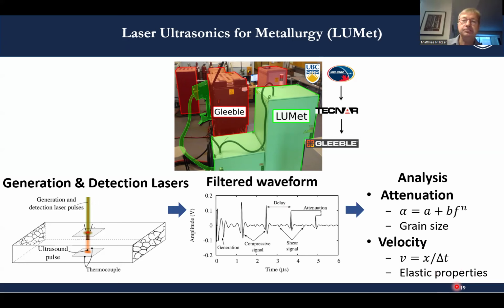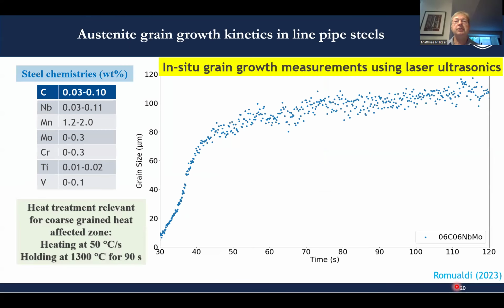when there is a texture change during recrystallization or phase transformation, we can record this as well. And we did high throughput studies for line pipe steels, where we looked in particular at conditions relevant for the coarse-grained heat-affected zone. We see here typical line pipe chemistry, so low carbon steels, microalloyed with niobium and also titanium, containing manganese, molybdenum, chromium at various levels.